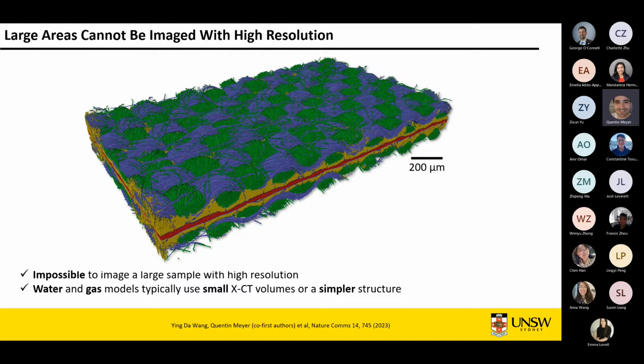Capture a large area. So this is a sample, probably about 1 square centimeter, and capture at high resolution. So in terms of hardware, it's simply not possible. So what people do when they want to model fuel cells is they either capture a very small part of this, say probably 200 or 300 microns area, which is the kind of size I was showing before, and then make a very complex Lattice-Boltzmann simulation on a very small area. Or you go a different way. You just forget about the real physical structure, and you make assumptions of what the physics is in your model, and you just go with purely physical equations and assumptions. So these two approaches are very valid. The problem with them is that when you make just assumptions, you may forget the physical challenges. When you use a much smaller area, you don't actually know if this small area you looked at was actually representing the entire sample.